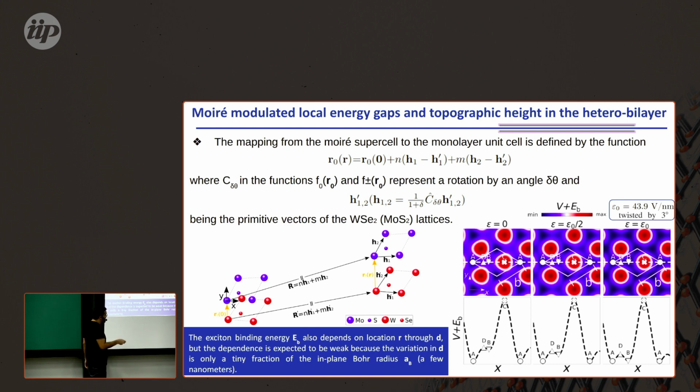And I would like to emphasize that by applying this electric field, there is a certain situation that we call critical bias voltage, in which the minima in A and B spots will be equal, at the same level, and this situation, as I go on showing you results, will present a very nice excitonic band structure.